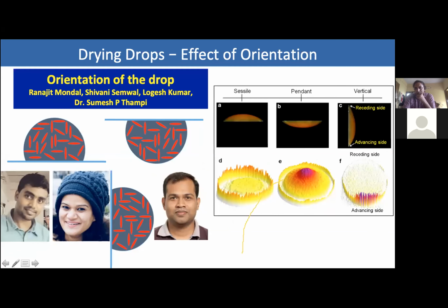And if you dry particles in a vertical droplet, in a vertical configuration, it turns out that more and more particles deposit at the advancing side of the droplet. Now, because we work with very small particles, the gravity effects are not important. Therefore, we know that these different deposits that we see here are not because of the gravity-induced settling of the particles. It is because of the gravity-induced deformation of the droplet.